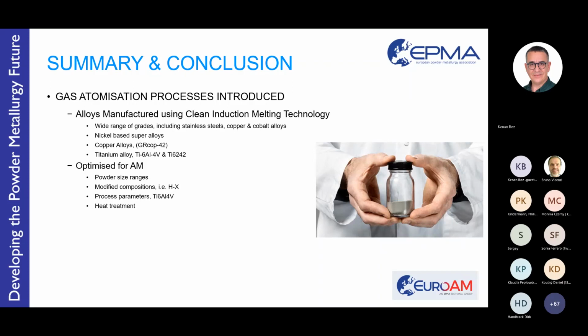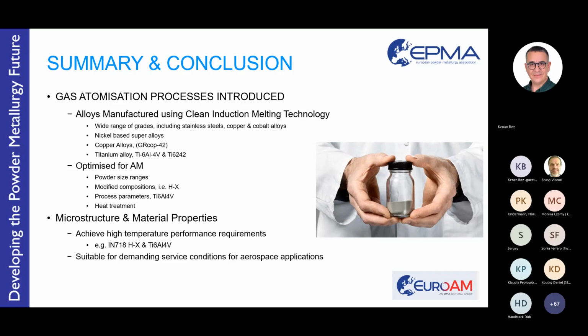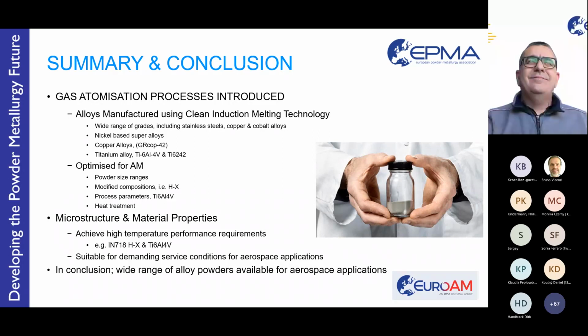Process parameters have been developed to increase efficiency, moving from 30 micron layer thicknesses up to 60 micron layer thicknesses, for instance. And all powders and alloys generally benefit from heat treatment to make sure that the differences and anisotropy between vertical and horizontal directions are reduced by heat treatment. And the microstructure and material properties achieve high performance requirements for the very demanding service conditions for aerospace applications. So in conclusion, there's a wide range of alloys available for additive manufacturing. Thank you very much, and I'll take questions at the end.